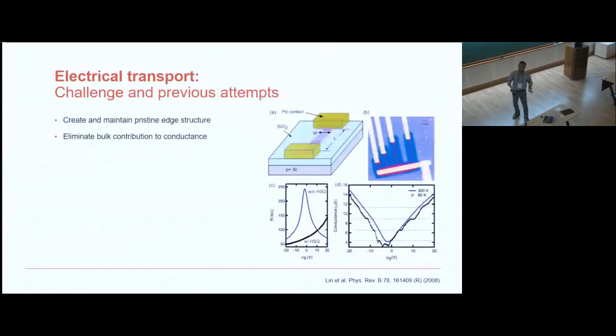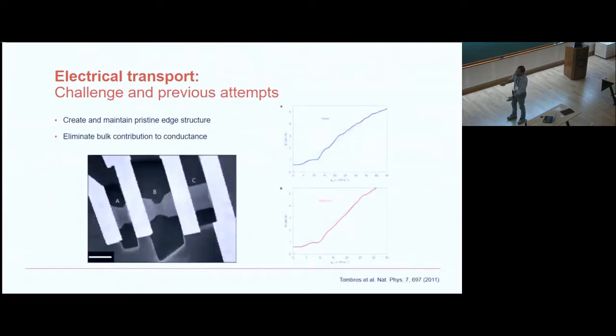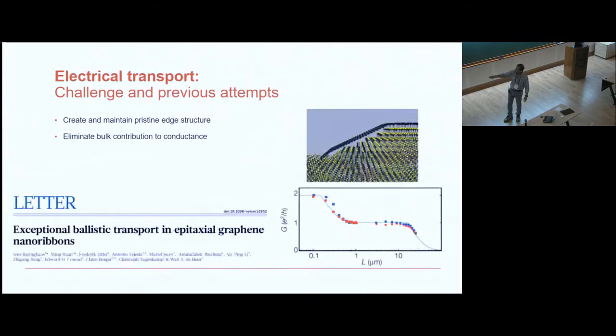Transport-wise, the experimental situation is very difficult. This is the IBM group. They made these nanoribbons to increase the quantum confinement gap, but they never saw the non-dissipative edges, simply because it was too dirty, the edges were too disordered. There were a lot of experiments, I'll not go through them. This was the Nature paper in 2016 from the Texas group. They essentially showed that if you have a nanoribbon with epitaxially grown graphene, then you will have very good quality transport, but that's not edge transport. Okay? You have very high quality ballistic nanoribbons, but nothing to do with the edges.